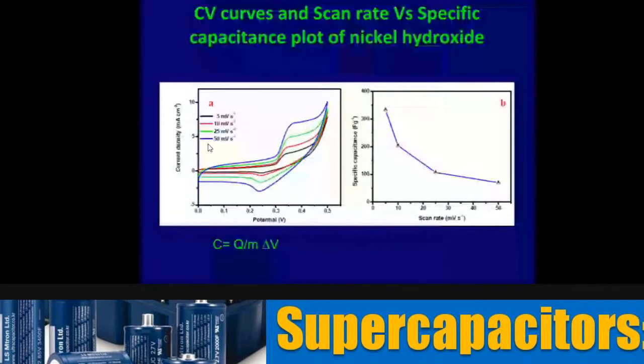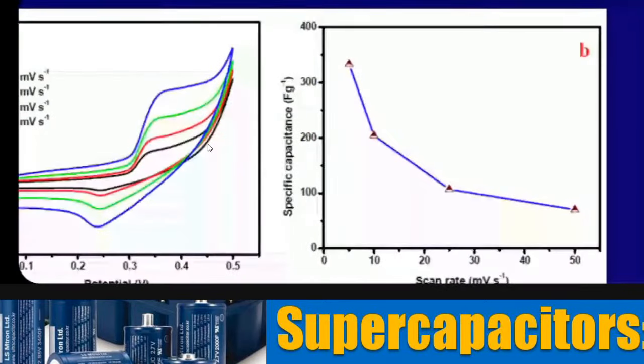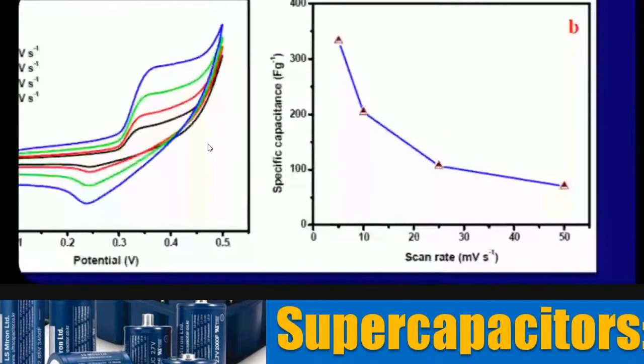But the interesting part is on the right-hand side. The right-hand side gives you a pattern where the capacity is plotted against the scan rate. Most of us have a feeling that the capacity is constant, irrespective of the rate at which we are charging a capacitor. But interestingly, we see that the capacity depends on the rate at which you are charging. The capacity is about 350 farad per gram at 5 millivolt per second, whereas when you go to 50 millivolt per second, it comes down to about 90 farad per gram.